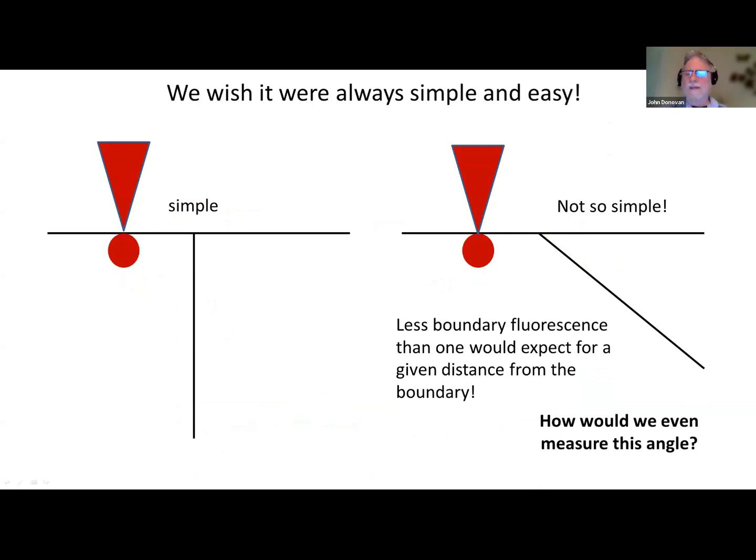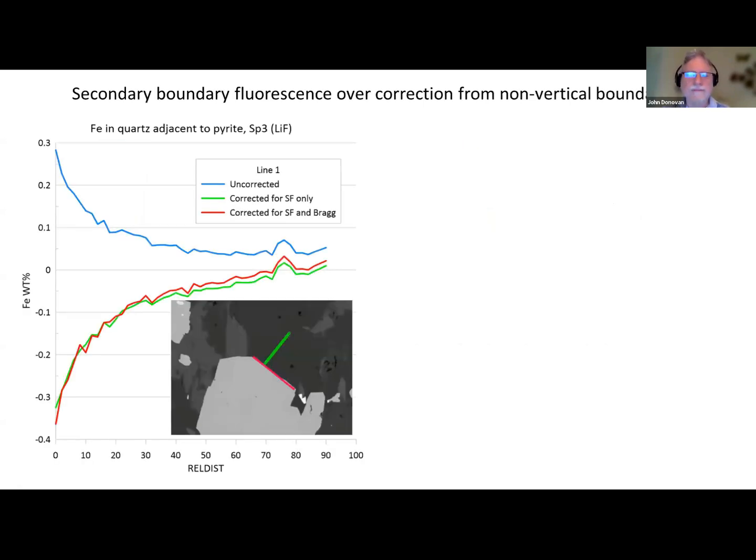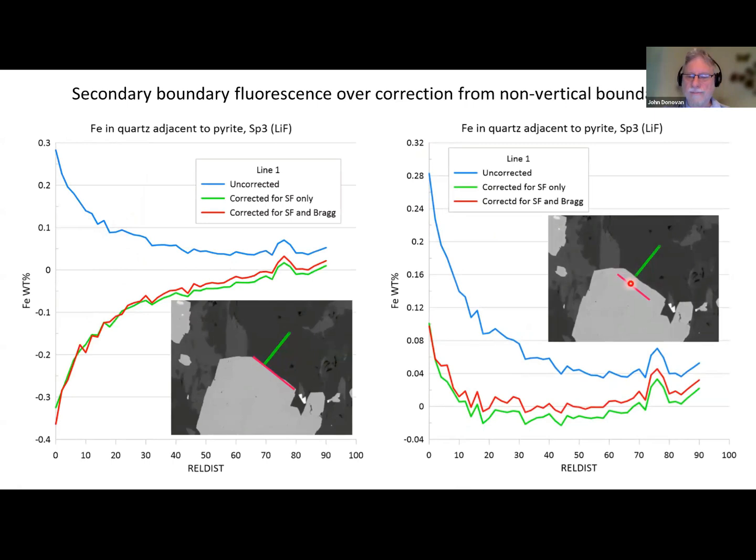You need to have a SIMS depth profile, and then it's destructive. So you've lost it now. Just to point out in this particular example that Glenn did for me, this material here, I believe, is a very sloped interface, because if I apply the boundary right there where it appears to intersect the surface of the sample, we actually overcorrect enormously. But if I move the boundary over to here, then it does a pretty good job.